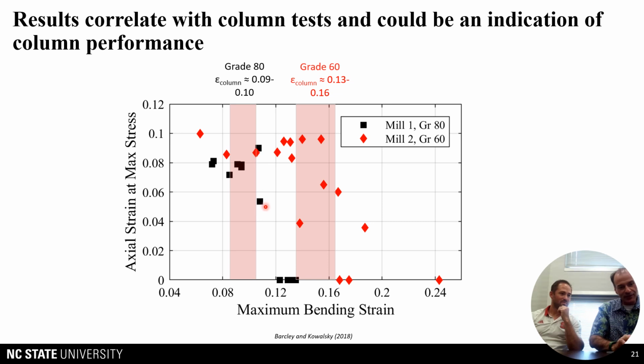So here you can see where it drops, where the cursor is. You can see that at a level of about 10% critical bending strain, it just becomes brittle. So right around this point, and that's very close to what you were seeing in your columns, Leo. And then for Chad's test, you see it's ductile, the rest is brittle down there, and the transition is somewhere in there.